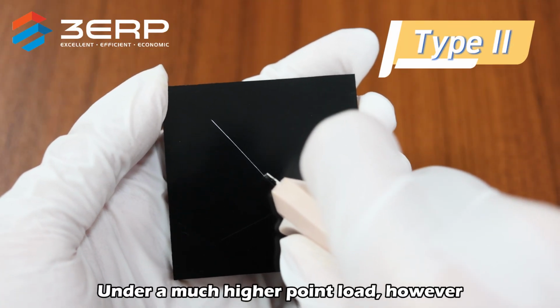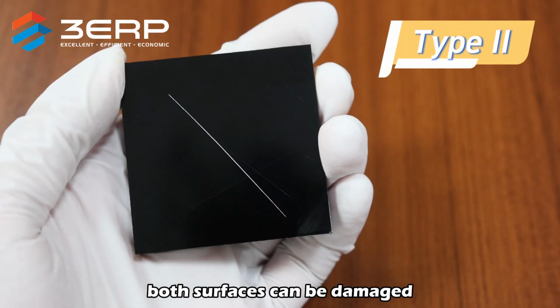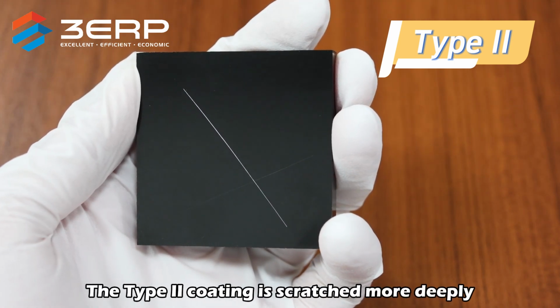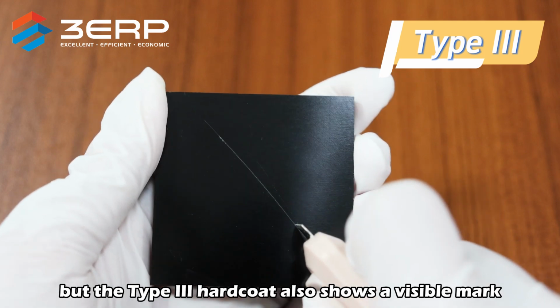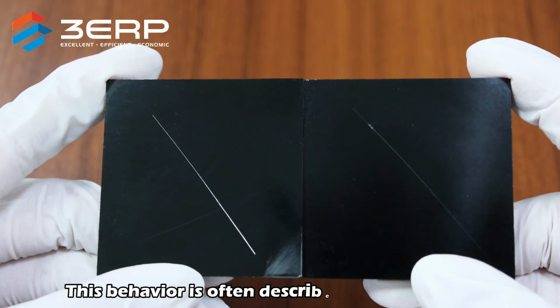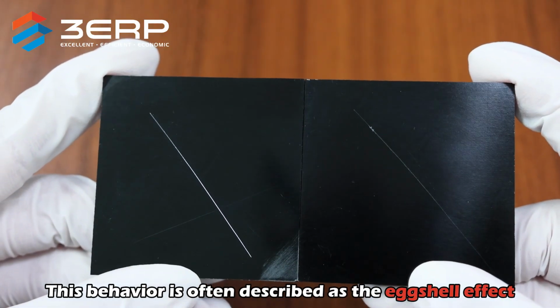Under a much higher point load, however, both surfaces can be damaged. The Type 2 coating is scratched more deeply, but the Type 3 hardcoat also shows a visible mark. This behavior is often described as the eggshell effect.